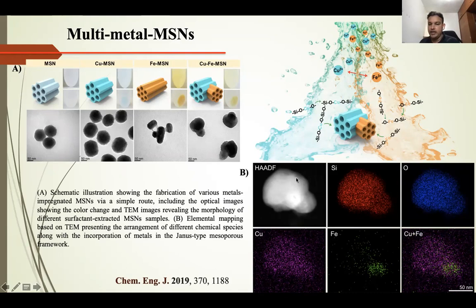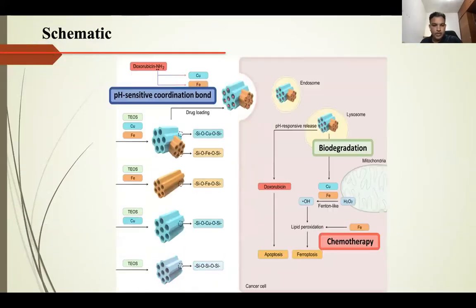And it was even confirmed by the EDS mapping, where you can see the iron accumulation is pretty high in the horn-shaped part, whereas copper is distributed all over, but iron is concentrated on the external end, because of the repulsion between copper and iron. This is the schematic showing this. The first one is normal silica, which creates a hexagonal MSN, and copper also created the hexagonal one, but the iron, strangely, formed a long rod-shaped MSN. Whereas the combination of these two, copper as well as iron, resulted in a Janus type.